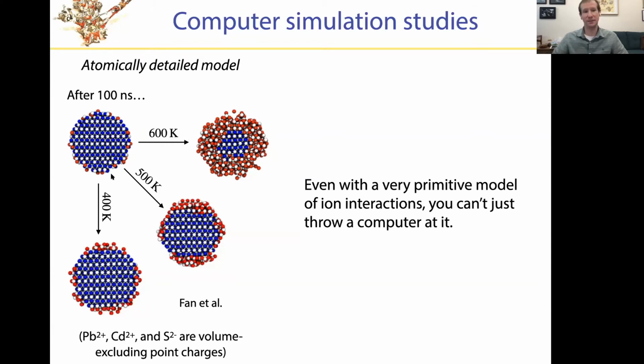That doesn't stop people from trying, and it's kind of interesting to see what happens if you take a representation of a cadmium sulfide nanocrystal, and try to watch its exchange of cadmium by lead ions. This is not even doing electronic structure calculations. This is a really primitive representation of the interactions within this nanocrystal. And even here, we can't get anywhere near the timescale over which cation exchange naturally happens. So even though it doesn't take the age of the universe, it does take many seconds. And to a molecule, that's a long time.